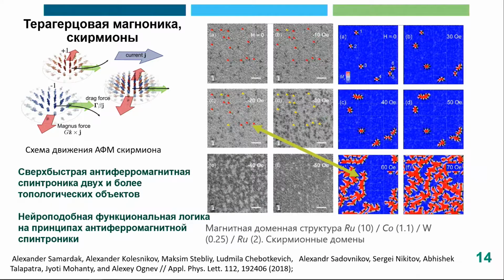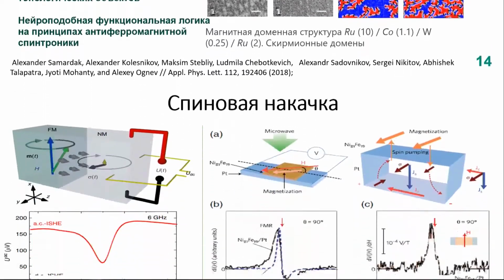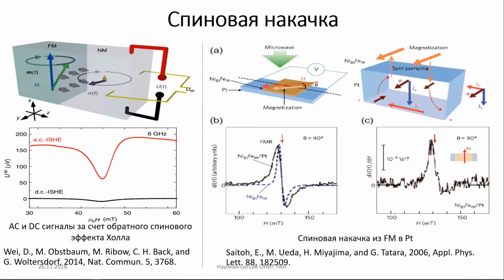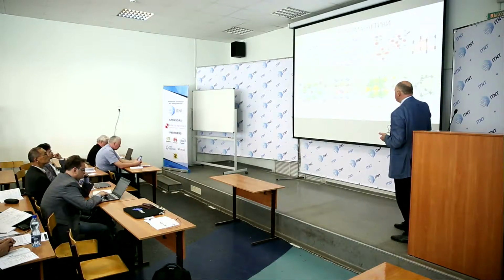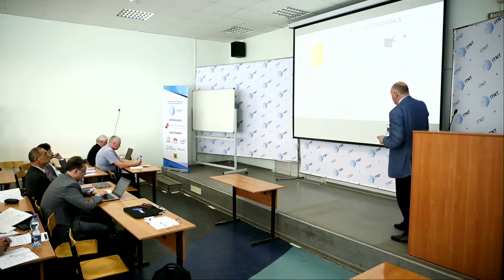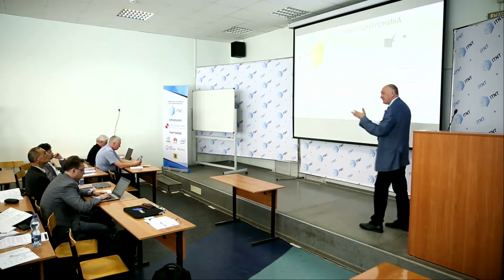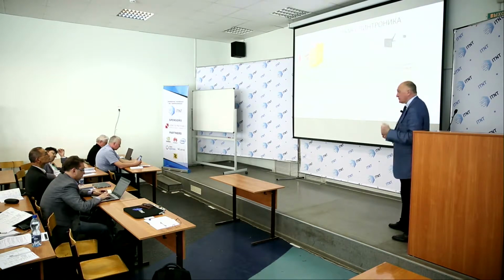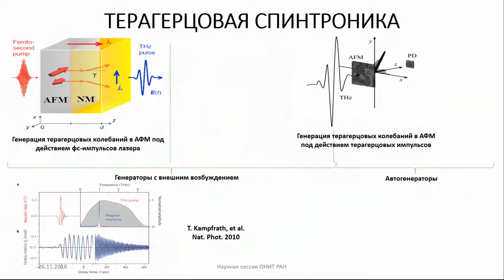If we can manage this exchange interaction somehow by, say, parameters of the shape of the magnetic field, therefore we can excite or receive electromagnetic waves in the frequency range of terahertz. How, for example, can it work? I will show simply. One possibility is to use an antiferromagnetic material and a normal metal, or heavy metal, which can be palladium, for example, or some other materials. And this material has a very strong spin-orbit interaction.